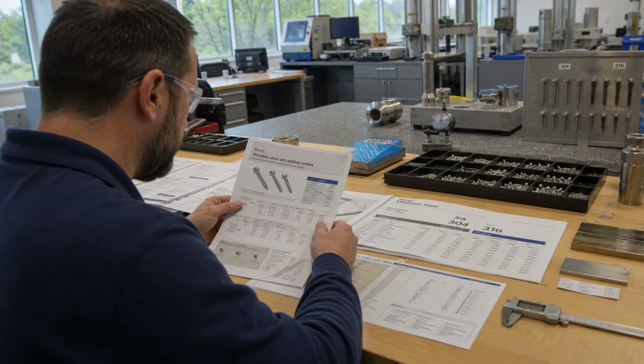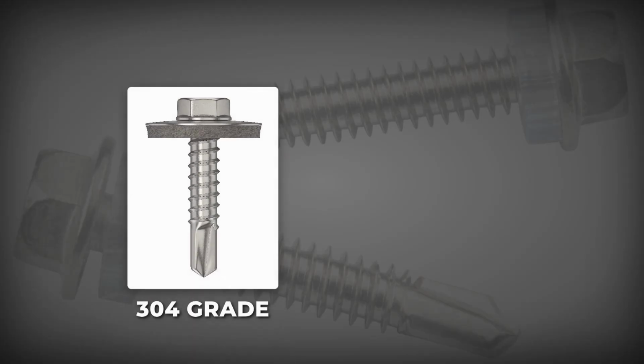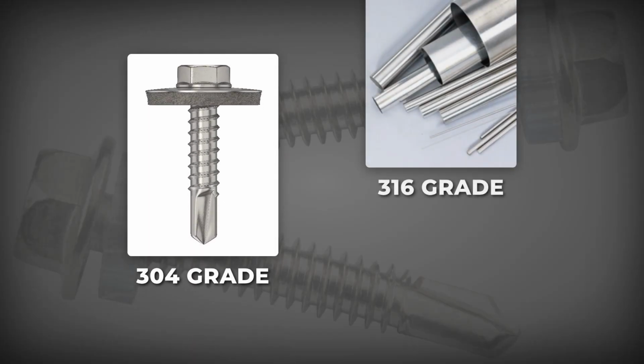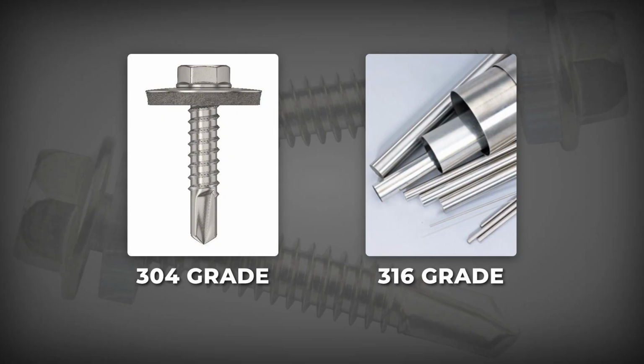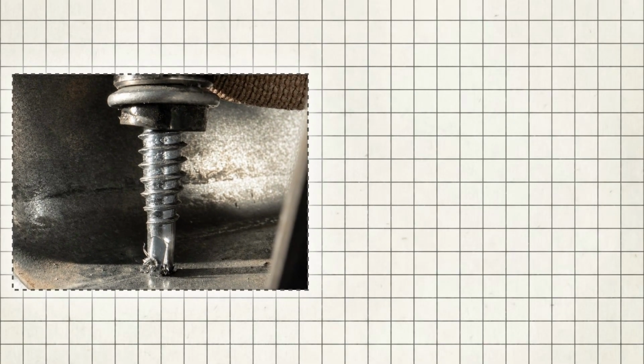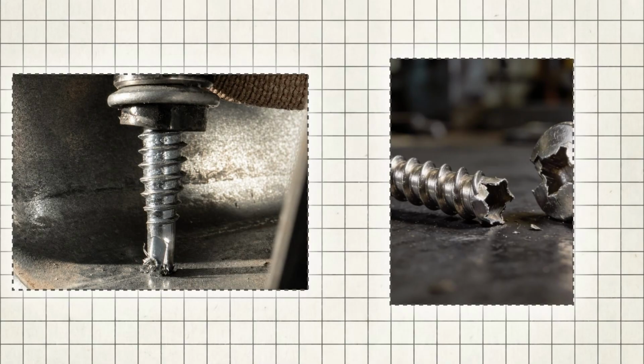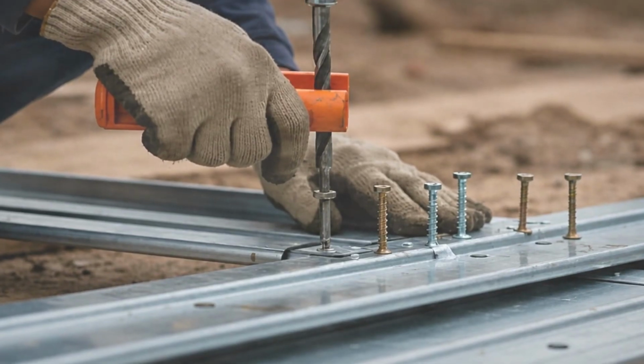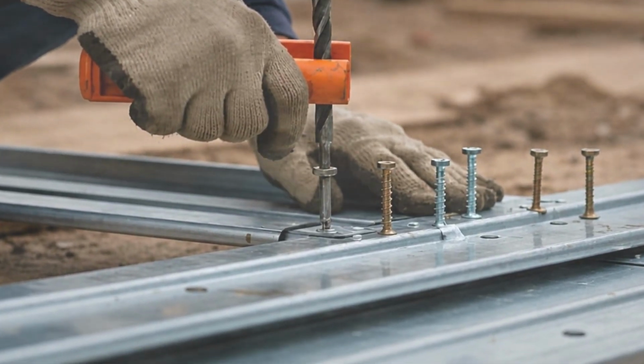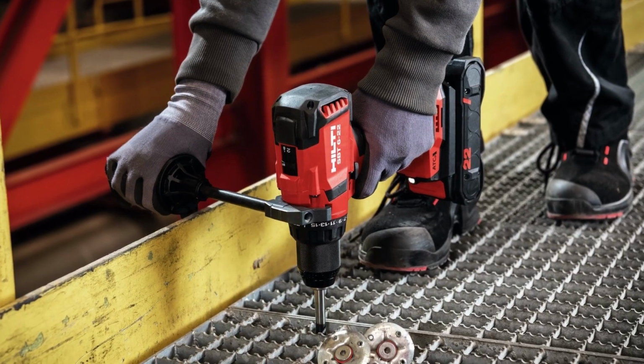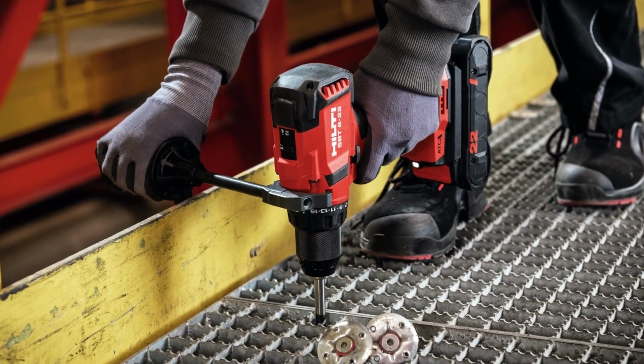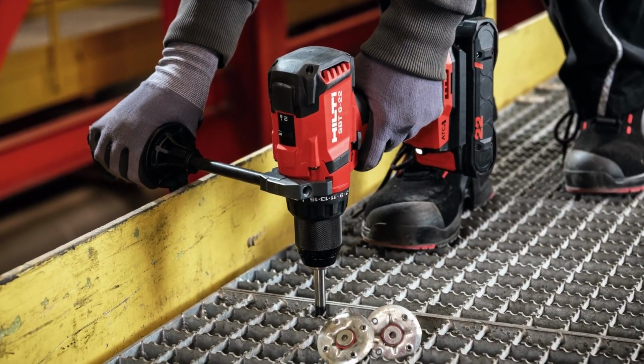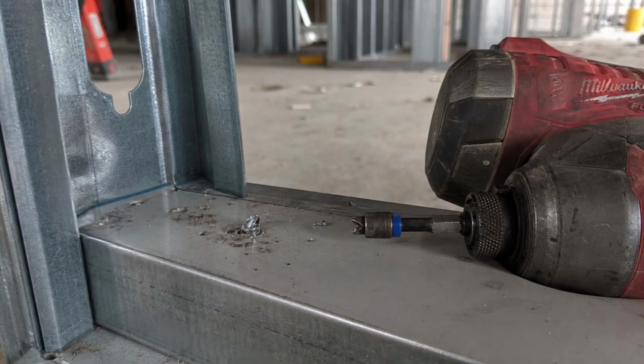Fastener manufacturers state the consequence plainly in their own literature. Stainless self-drilling screws are made from 304 or 316 grades. Those grades cannot be hardened, and the drill point can therefore only cut into softer materials like aluminum. They also flag the assumption that costs people money on job sites. It is a common error to believe that a stainless self-drilling screw will drill into steel. It will not. The point deforms, the flutes clog, the screw work hardens the hole it is failing to make, and eventually the head twists off.